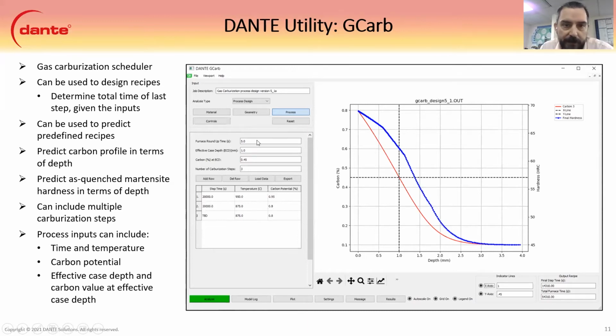Not too much difference. Same roundup time, same effective K-step that you would need, the carbon at that K-step, and then the total number of steps. And that gives you the same kind of output here. It'll give you the as-quenched martensite hardness. And for here, we were targeting 1 and 0.45. So that one pretty much nailed it.